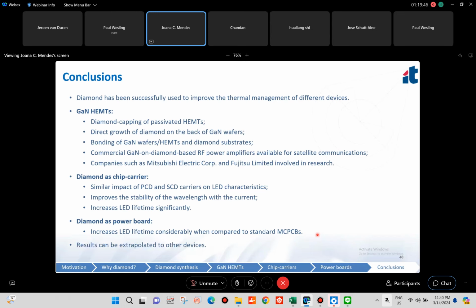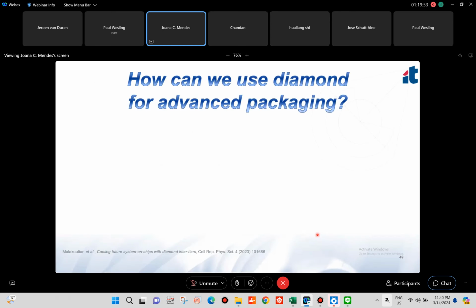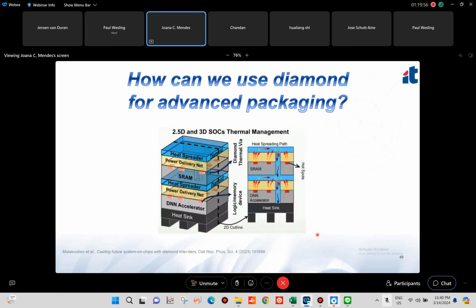And now, of course, we can extrapolate results to other devices. And now I leave here a question. How can we use diamond for advanced packaging? And I come up with a recent proposal that was made by Stanford University, where they proposed to use diamond inter-tier heat spreaders and diamond thermal vias. So with the heat spreaders, we manage to homogenize the temperature of the hotspots, but then with diamond thermal vias, we can actually spread the heat from one tier down to the other until we reach the heat sink. And they estimate huge improvements in the efficiency and temperature in the case of high performance computing.